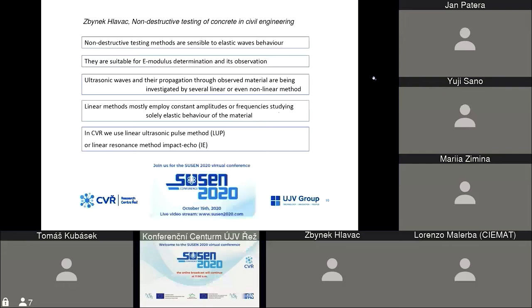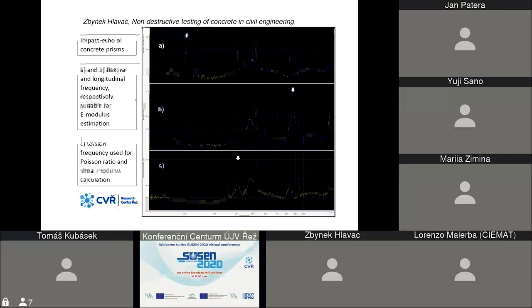The opposite is nonlinear, because then I'm changing amplitudes and changing frequencies. Linear methods which we use and which we developed in CVR are the ultrasonic pulse method and the resonance method, impact echo. I'd like to introduce impact echo, which is part of the resonance method. You impact the tested sample and you have the answer, the echo.